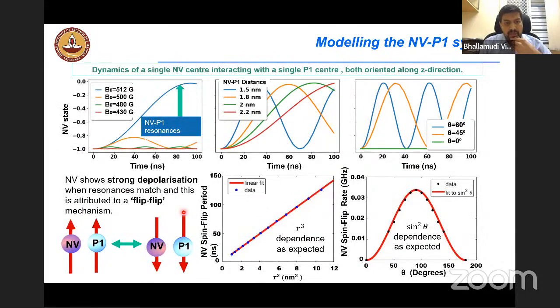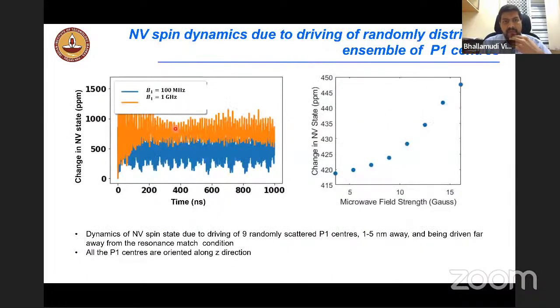But the main thing is that we find there's a flip-flip mechanism that allows coupling between the two spins. And in this particular case, because the resonant frequencies match, we see some coherent oscillations, and we can find the usual 1/r³ dependence. And we find that basically we can verify our simulations are working nicely. And based on that, we are now applying them to understanding the spin dynamics where the NV and P1 are off resonant to each other.